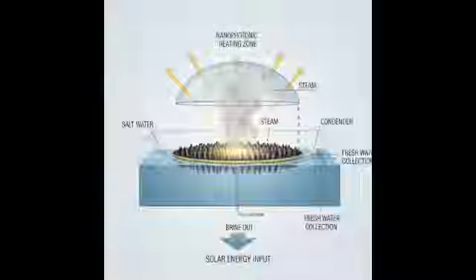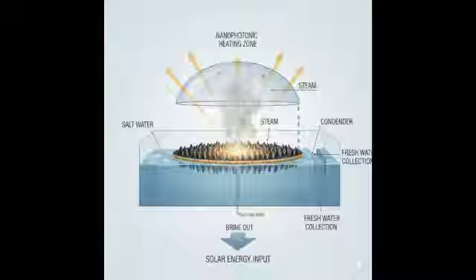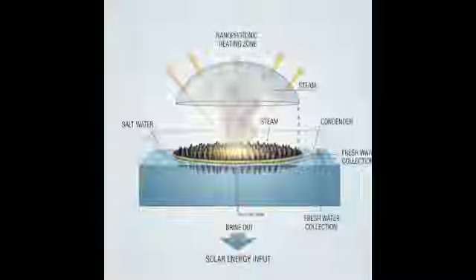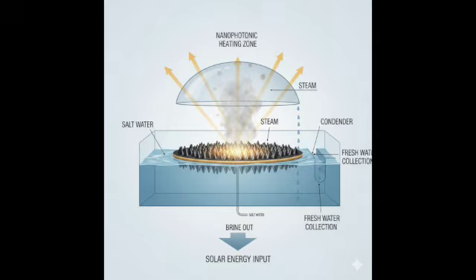Let's talk module design first. Right. The physical design of the module itself matters a lot, particularly in PMD where you're relying on surface absorption. One key factor is the depth of the water layer in the feed channel. Why does that matter? Because if the water layer flowing over the photothermal membrane surface is too thick, the water itself can refract and scatter the incoming sunlight before it reaches the active layer, reducing the energy that actually gets absorbed and converted to heat. Exactly. So shallow feed channels are generally preferred in PMD designs to maximize light penetration to the photothermal surface.